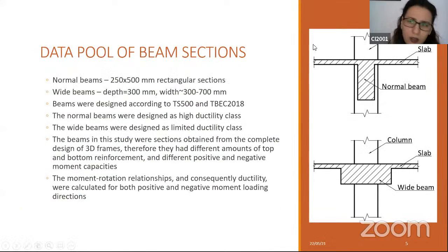So in here we have schematically shown the normal and the wide beams. Our normal beams all had a section of 250 by 500, while the wide beams had a depth of 300 and the width varied from 300 to 700 millimeters. All these beams were designed in accordance with the Turkish standards. The normal beams were designed as high ductility class, and the wide beams were designed as limited ductility class.